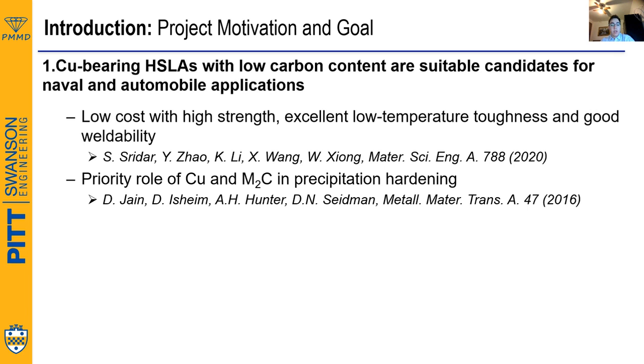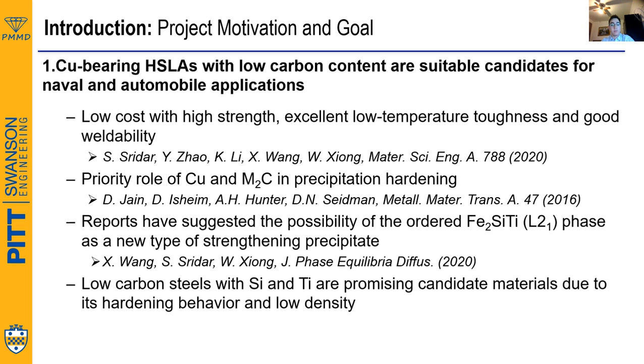Now, in recent years, there has been an effort to explore precipitation hardening of steels with intermetallic phases. In particular, the iron silicon titanium system has received attention since it has been shown that it can form a high volume fraction of intermetallic precipitates. It has been reported that when titanium and silicon are added to low carbon steels, metastable Fe2Si-Ti intermetallic phase can precipitate. Studies confirm that this is an L21 order phase able to precipitate in much higher volume fraction, even above 6%.